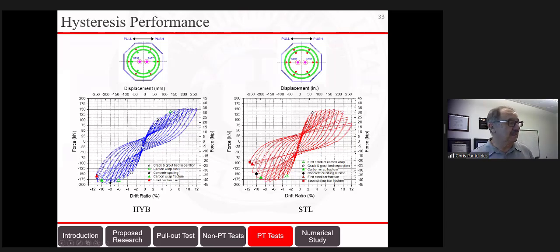So this shows the performance then of these two columns. You can see on the left, the hybrid column with the two post-tensioning bars gradually reaching a high peak force capacity of roughly 150 kilonewtons. And that happened at about 10% drift ratio. And on the right, you can see the steel column, which reached a very similar lateral capacity. But this capacity was reached earlier, at about 6% drift ratio. And in the end, it achieved a very high plateau, as you can see here, whereas the hybrid column doesn't have a plateau.